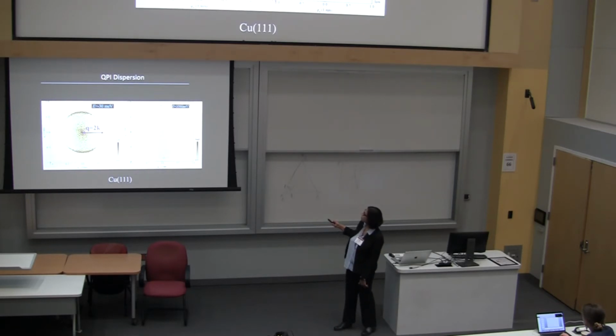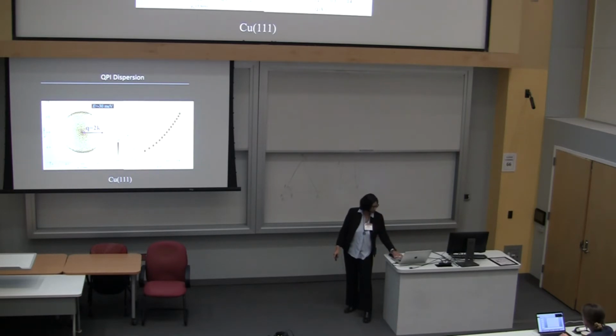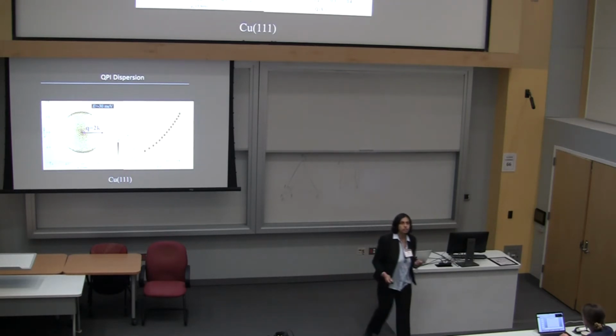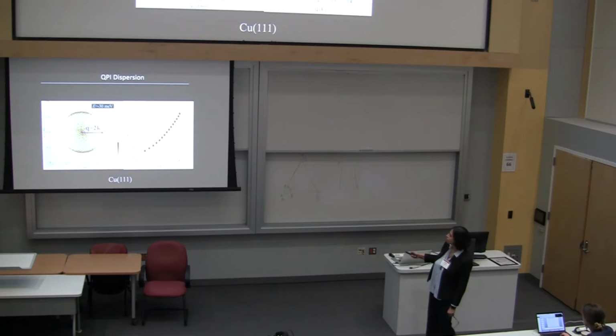So you get this circle that increases as a function of energy. This is above the Fermi energy. And you can plot the radius of the circle and you get the dispersion, energy versus momentum. And for the surface states on copper, you get parabolic dispersion.